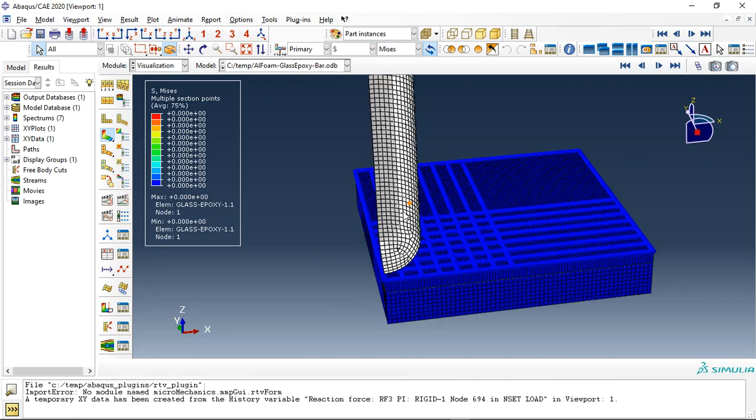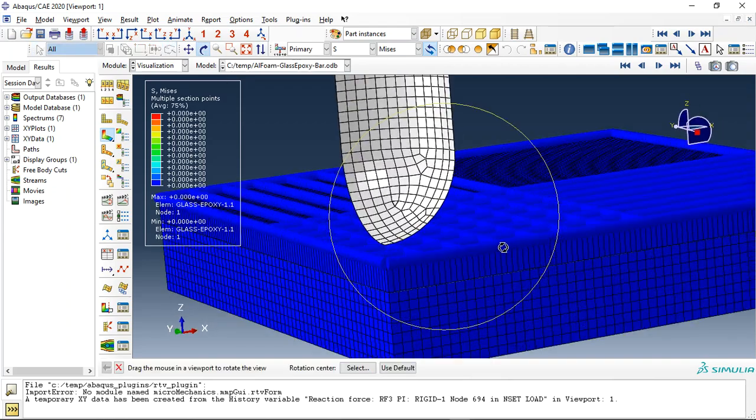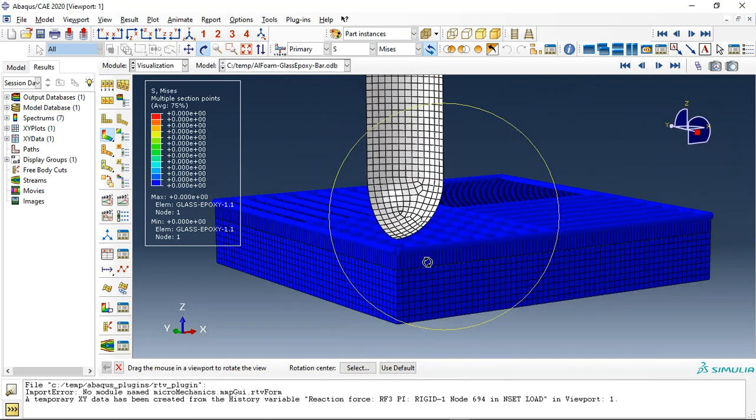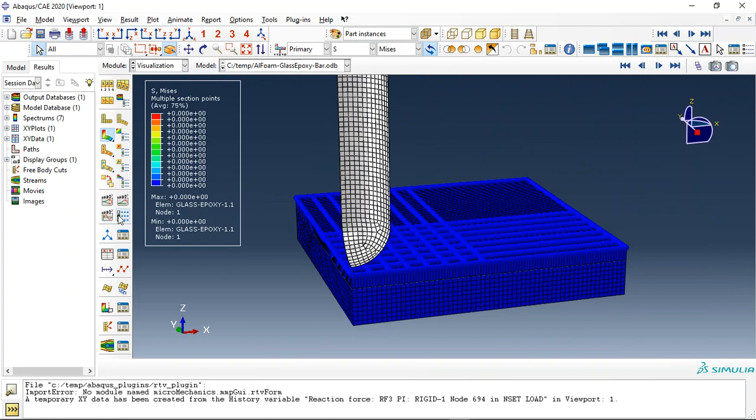Today I did a model of a rigid impact to the composite panel, which is made with a steel wire as a reinforcement at the top, then the glass epoxy fiber, and after that the aluminium foam. We use Johnson Cook model, hardening and damage for the steel reinforcement, Hashin damage criterion for the glass epoxy, and crushable foam coupled with ductile damage criterion for the metal foam.